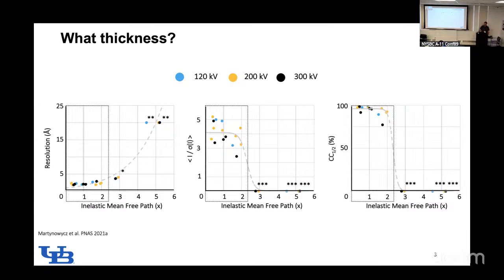And the only thing you really need to take away from this is that anything at 3 times the inelastic mean free path is basically useless. And if you want any useful data whatsoever, it should be about twice the inelastic mean free path or less. And the data actually peaks and is best at 1 times the inelastic mean free path.